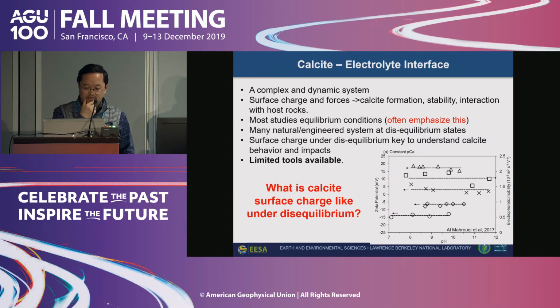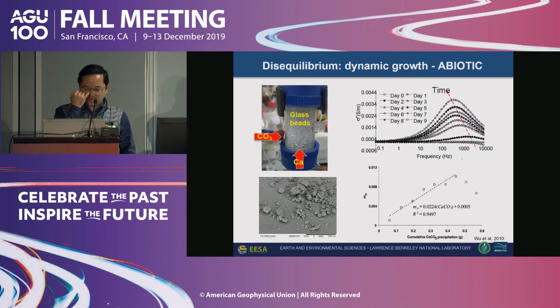So basically, the question we try to answer with low frequency impedance spectroscopy is what the calcite surface charge looks like under disequilibrium conditions, which is very transient and very hard to study because it's not stable. So we started with a very simple experiment a while ago, where we precipitate calcite by combining calcium and carbonate in an abiotic condition. This is an experiment conducted in glass beads. You can see that as time goes by, we have a very nice consistent increase of the impedance. This is the imaginary component over time, not only in the magnitude, but also a shift of the peak from higher to lower frequency. I'll talk about the link to the surface property later.